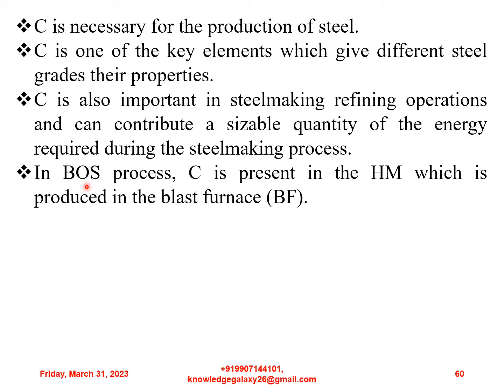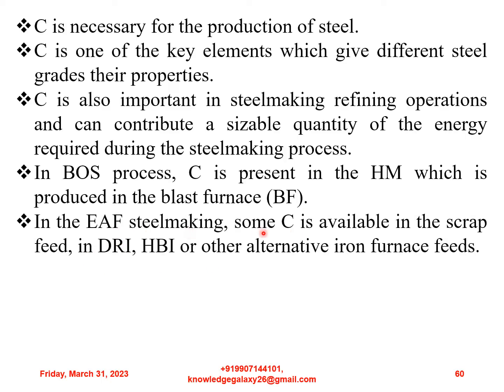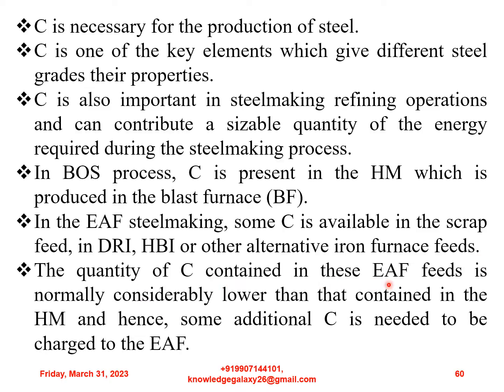In basic oxygen steel making processes, carbon is present in the hot metal which is produced in the blast furnace. In the electric arc furnace steel making, some carbon is available in the scrap feed, in DRI, HBI or other alternative iron furnace feeds. The quantity of carbon contained in these electric arc furnace feeds is normally considerably lower than that contained in the hot metal, and hence some additional carbon needs to be charged to the electric arc furnace.